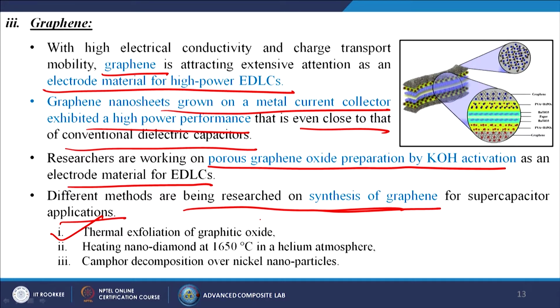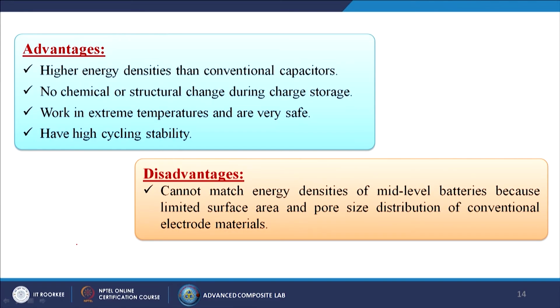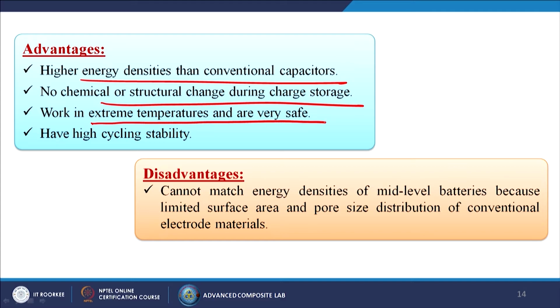They are making the reduced graphene oxides, as we generally call it, by heating nano diamond at 1650 degrees centigrade in a helium atmosphere, an inert gas atmosphere, and the third one is camphor decomposition over nickel nanoparticles. What are the advantages? High energy densities than conventional capacitors, no chemical or structural change during charge storage, work in extreme temperatures and are very safe, have high cycling stability. Of course, there are certain disadvantages: they cannot match energy densities of mid level batteries because of limited surface area and pore size distribution of conventional electrode materials.